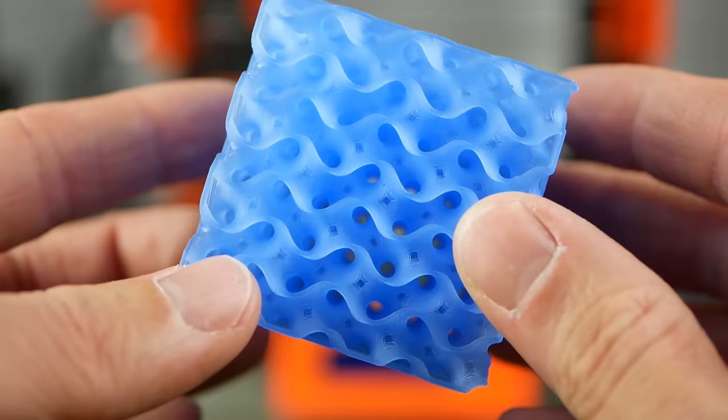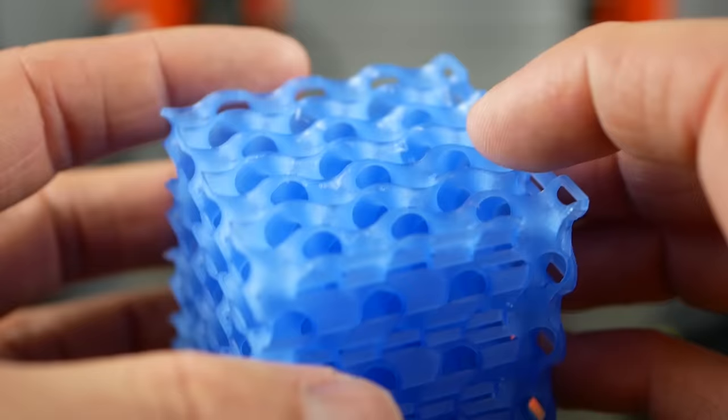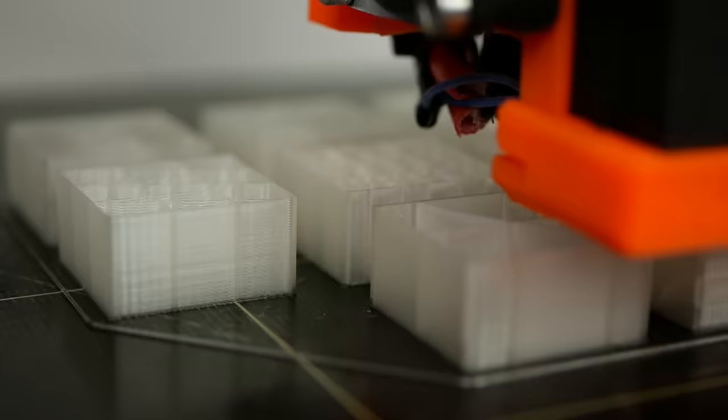For the 3D infill patterns, 3D honeycomb is dead in my opinion. Cubic and gyroid infill performs pretty much the same, just the infill spacing is a little denser with the new contestant and, come on, it definitely looks cooler. So in summary, I probably might be using line infill for any aesthetic parts and anything that will see some load, gyroid infill might be the new way to go due to its good and uniform strength in all directions.